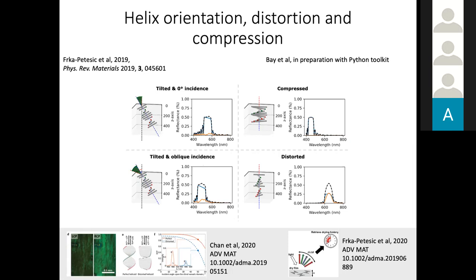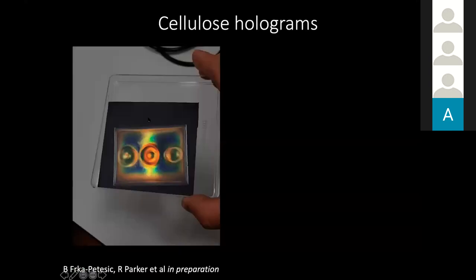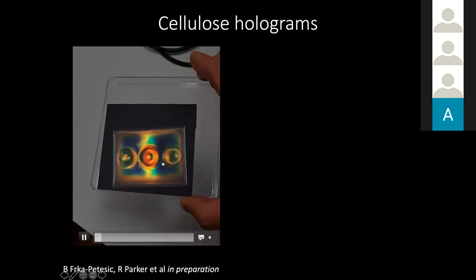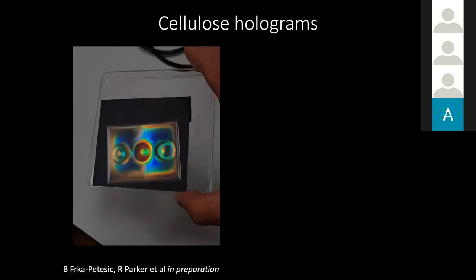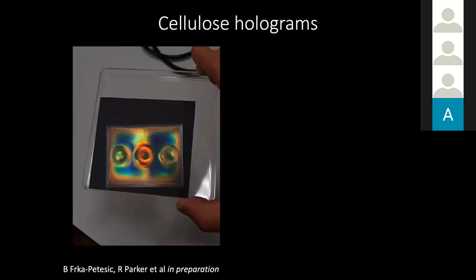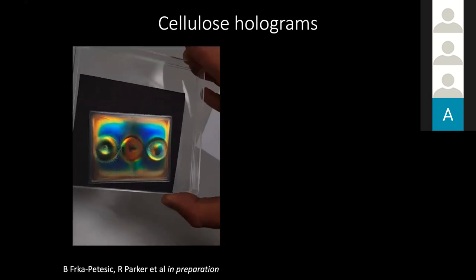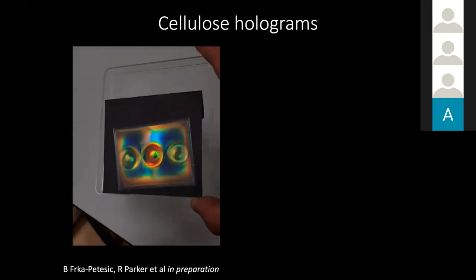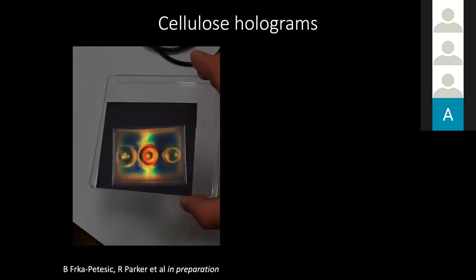That's the trick. And this is because, again, as I was explaining to you before, it is a photonic structure, it's an ordered system. So if you change the orientation of the crystalline structure, in this case the crystalline structure is a helicoidal one, you can change the color in terms of dimensionality, on directionality. And this is essentially what holograms are doing. When you look at them from a different direction, you see different colors. So it gives you the impression of being a three-dimensional structure, even if it's only a flat film.